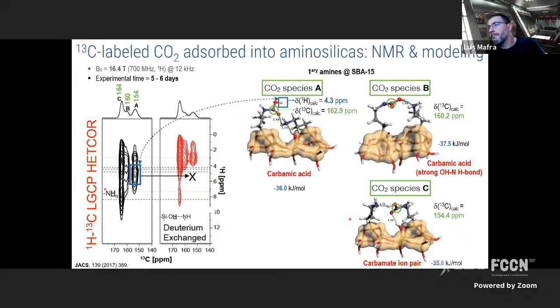At the end, the three lowest energy models are these ones that are depicted in the slide. And I was glad to see that for the species A, calculations came up with the chemical shift at 4.3, which is exactly the one that disappears upon deuteration. So this is a very labile proton that can be exchanged by deuterium, and this helped us to assign this proton environment. This was very strange because usually carbamic acid protons like to be engaged in hydrogen bonds like the other ones here. But this one is not engaged in hydrogen bonds somehow, okay? It was a bit puzzling at the beginning, but there is no other chance to have this kind of chemical shift if we don't have this proton in this specific arrangement.